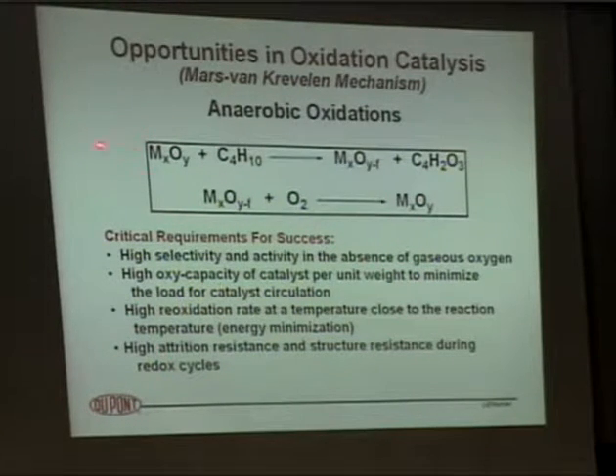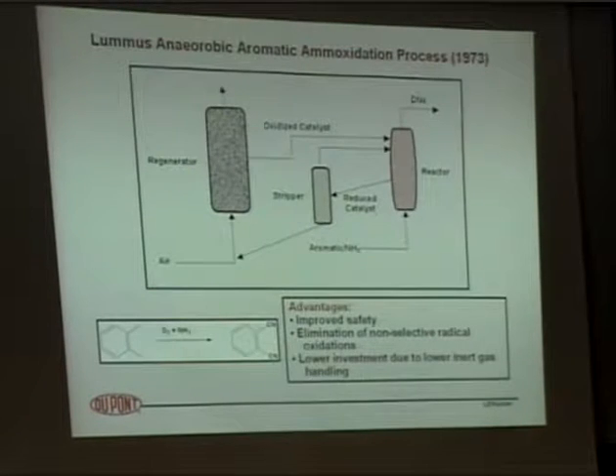The catalyst is the most important, most costly part of this overall process. If the catalyst is not attrition resistant, if it falls apart, if it doesn't stand up to millions of cycles, then the process is also uneconomical, because these catalysts are not cheap by the time you get them from companies like Sud-Chemie and Degussa and others. So you've got to make sure the catalyst stays in there for a very, very long time. Now let me give you some examples where this has been looked at over the years.